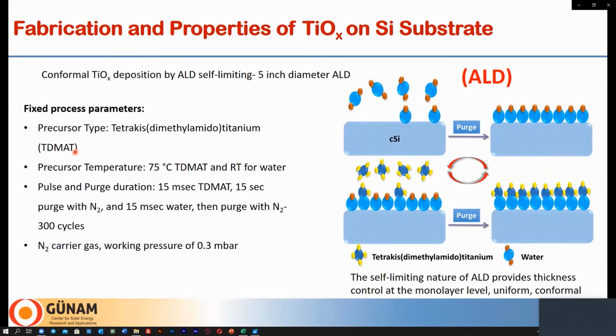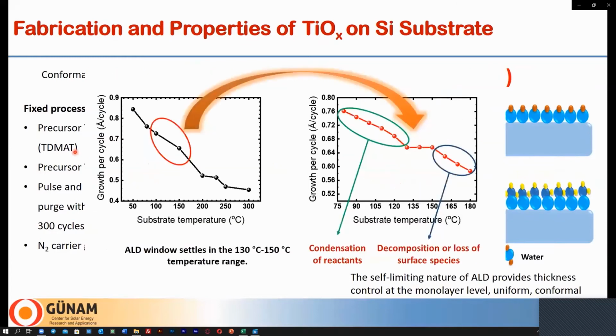We used this process with TDMAT as the titanium precursor and water as the oxidizer. But first we identified the ALD window. Here is the ALD window where the growth saturates, and we found it between 130 and 150 degrees. At temperatures below this window, we have condensation of reactants, and above this window we have loss of species. But as we will see later, the film deposited at high temperature gives better results.